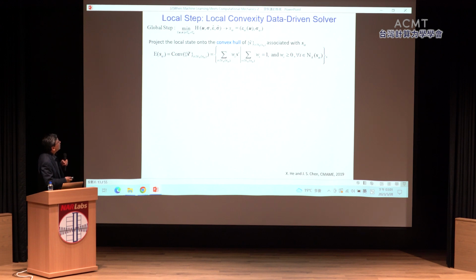Okay, so then from there, what we propose is to construct a local convex hull. With this local data reconstruction and with a given physical state, I can look into the local nearest neighbors, and I will then construct a convex hull. And convexity is nice because, first of all, the weights are supposed to be non-negative. They all sum up to 1. So you really have this convexity property that guarantees stability of this data search.